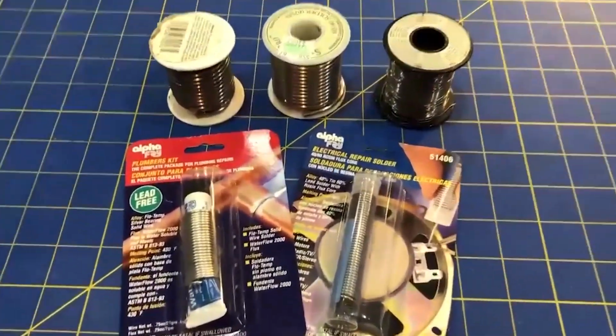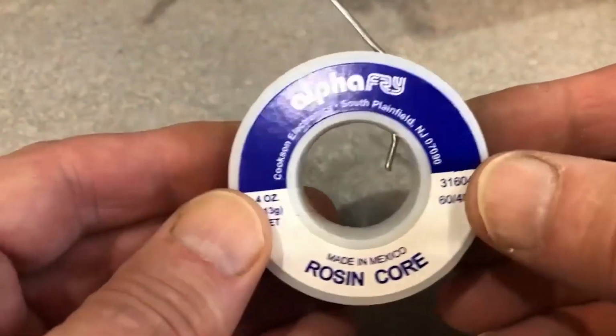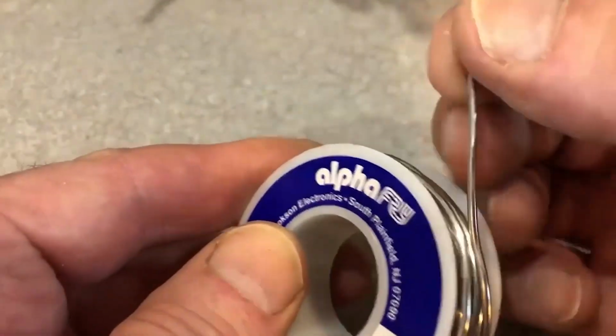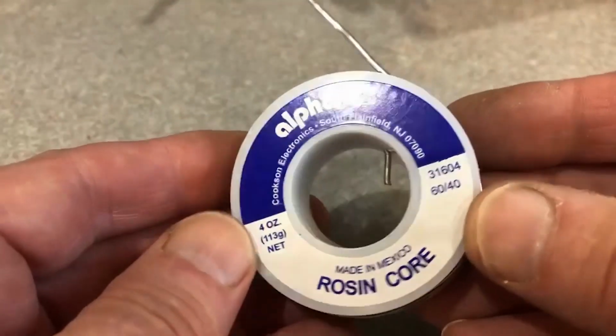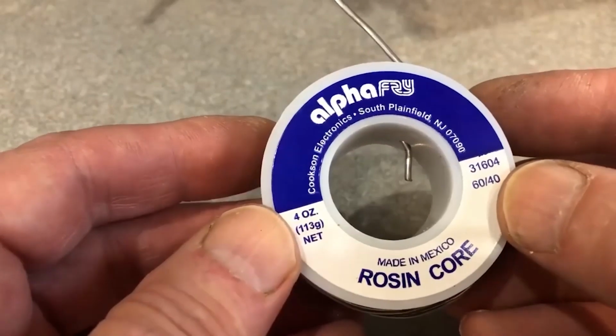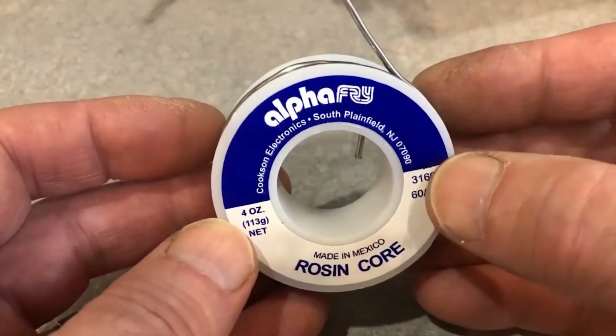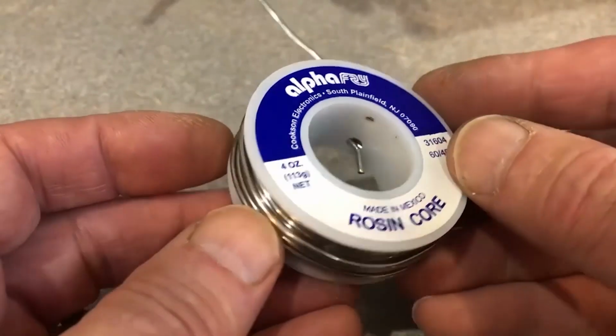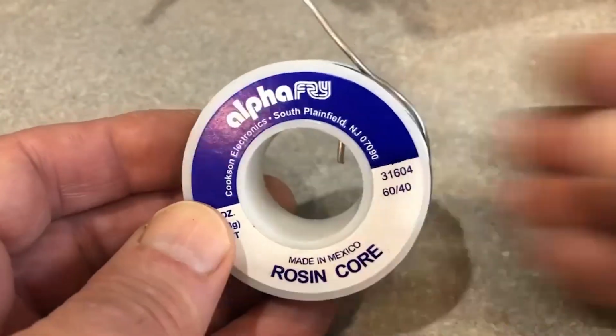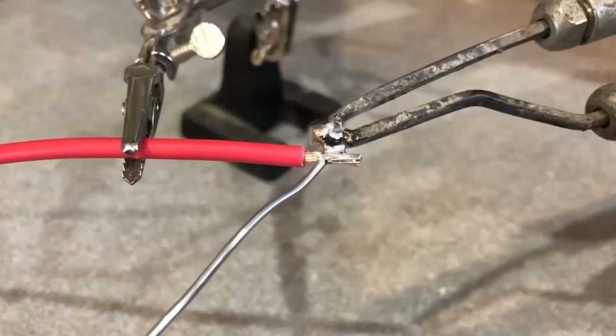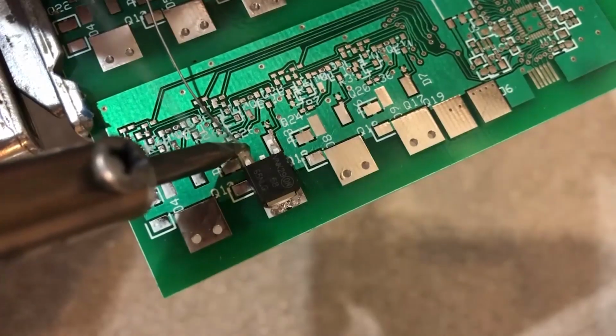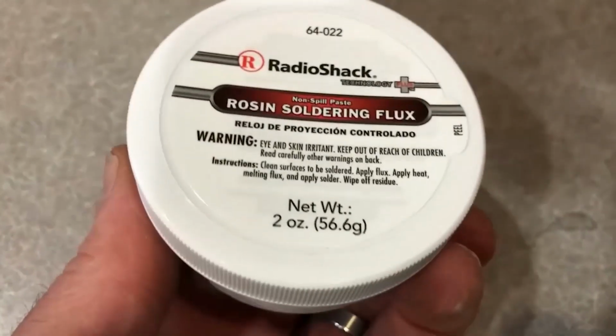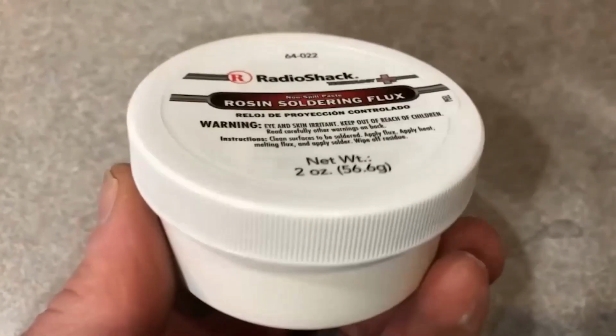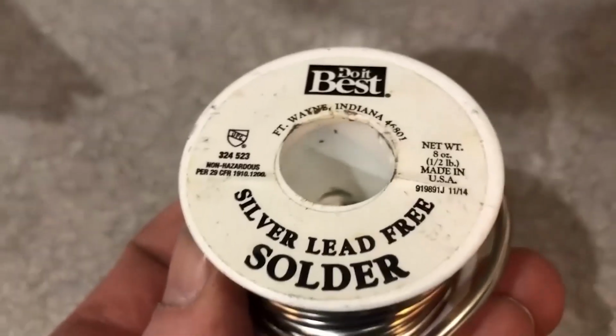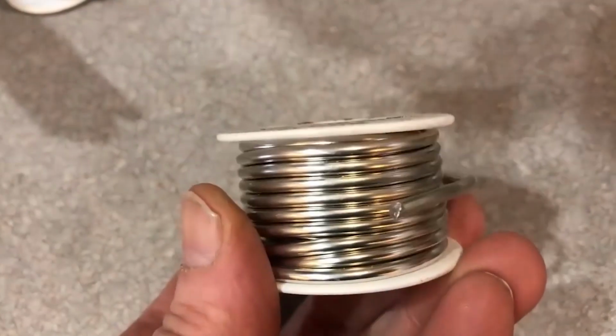So what's an appropriate soldering flux? This is your typical 60-40 rosin core solder. It contains 60% tin and 40% lead, and turns liquid at about 370 degrees Fahrenheit. The rosin core works as a shield to prevent oxidation while soldering. This solder is designed for use in electronics, mainly soldering wires. I use it on circuit boards and pretty much anything electronics related. I also use this type of resin flux to help flow the solder when the rosin core in the solder is just not enough. As solders go, it's not very strong, and it contains lead.